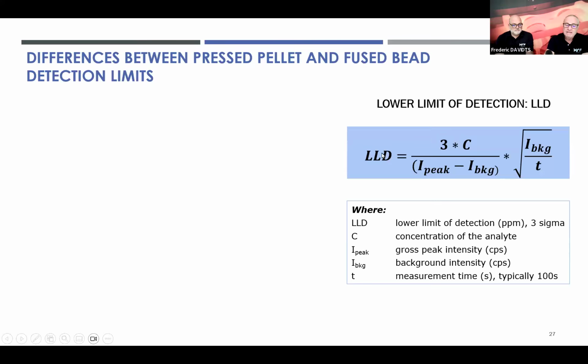Now, there is a difference between the pressed pellet and the fused beads methods, for those who have seen both webinars, and especially when it comes to detection limits. First of all, we need to know what the lower limit of detection is. This is defined by this formula, in general. There can be some more parameters in there, but anyway. So we really depend on the peak to background ratio and the measurement time to define our limit of detection.